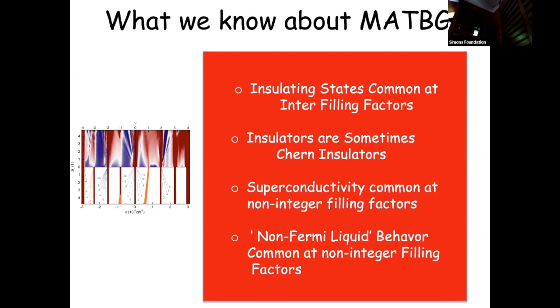Superconductivity is all over the place and common when we're in the metallic regime, at non-integer filling factors. And interestingly, the resistivity, when we're close to these magic angles where all this strong correlation physics occurs, has surprisingly strong temperature dependence at low temperature.